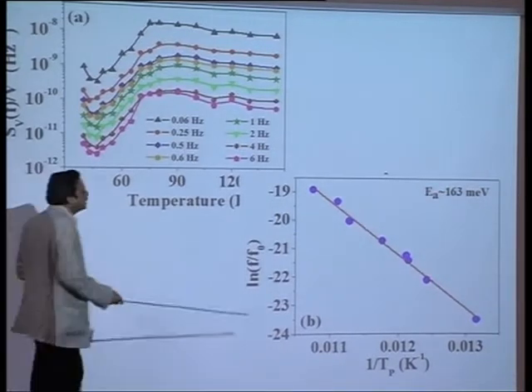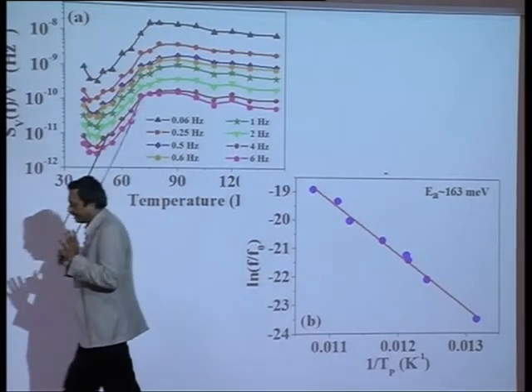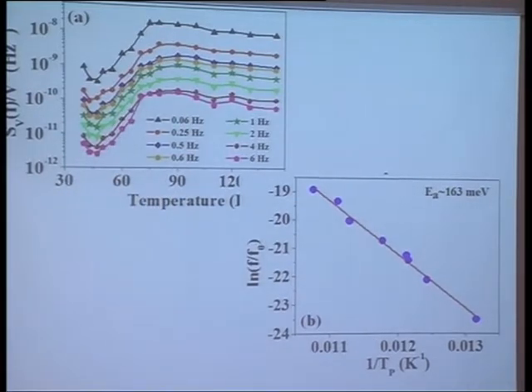But the important point is this activation energy. Look at this scale. It is tantalizingly similar to this Coulomb gap scale. And this is exactly, I think, the important discovery that we had from this experiment, that there is indeed a kinetic freezing of the fluctuation, and the scale of the freezing is dominated by the Coulomb gap. When we first did the experiment, we thought that it is just an accident. Then you vary the composition, and that changed the delta CG, that changed the EA. We did find that these numbers are close to each other.